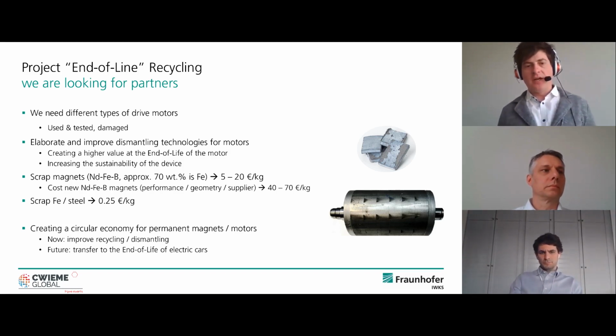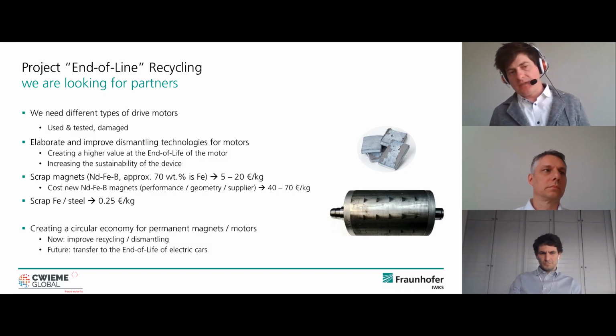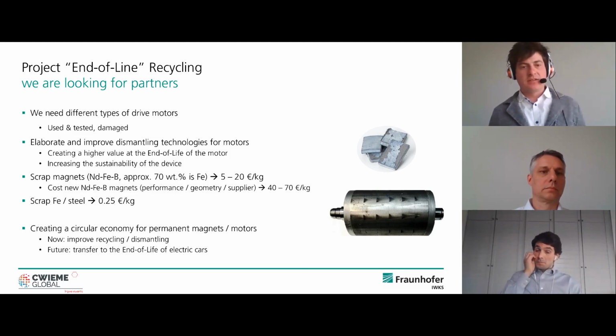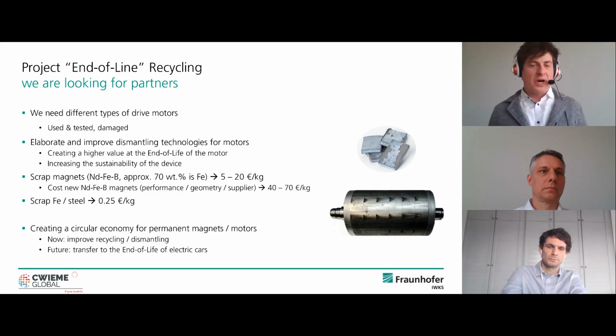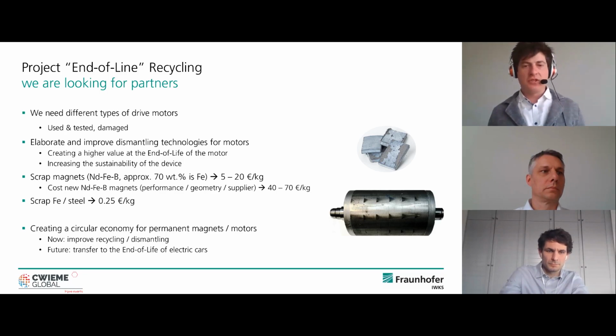Just to give you an idea, our impression is that we can increase the value of the end-of-life device, the motor, with such a project. We can also increase the sustainability, since the magnet is not dumped, it's recycled and used for another kind of product. When you buy sintered magnets nowadays, independent of performance, geometry and supplier, you will pay something like 40 to 70 euro per kilogram of neodymium iron boron magnet.